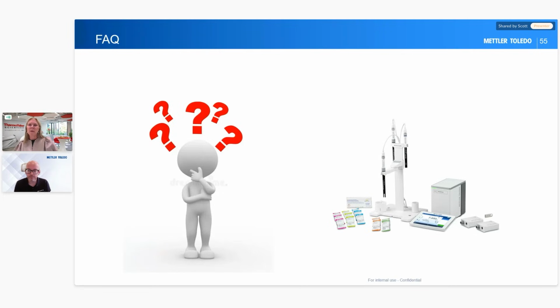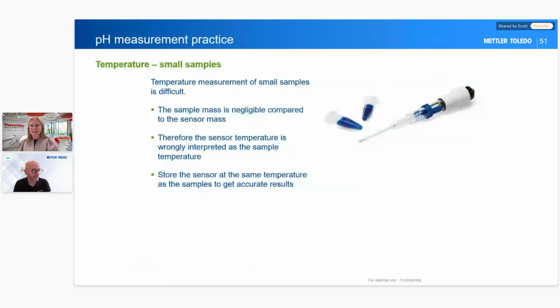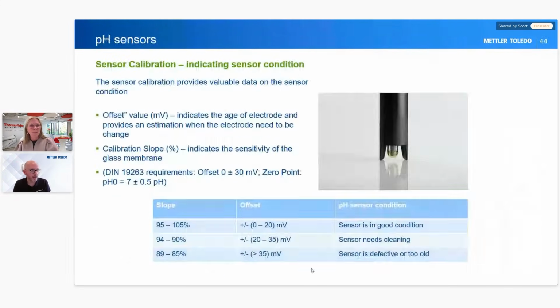Then we have a question from Sophia: if the slope is fine, but the offset is getting higher, with a slope of 99.5% and an offset of minus 12.5 millivolts, is there something that can be done, or is it just to change electrodes? If I remember correctly, I don't think anything needs changing with that electrode. So if I go back, perfect. There we go. You can see a slope of 99.5 and an offset of minus 12.5 millivolts is absolutely perfect. The sensor's in good condition, so in that case, you don't need to change or do anything. It's only when it gets to plus or minus 20 millivolts, or plus or minus 5% slope, not 0.5%, but 5%, that it needs changing or looking at. So if what you've written there is correct, then your electrode is absolutely perfect and in great condition.